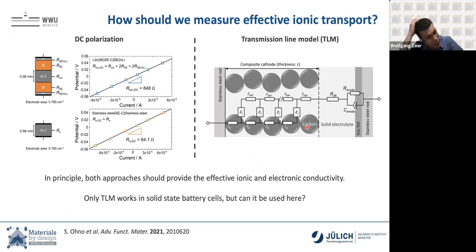Now there's in principle 2 ways that we can measure this. The simpler way that we use most of the time is so-called DC polarization. In the end, you polarize your setups with an electron blocking current collector and an ionic blocking configuration, and you just measure ion currents. So you use Ohm's law and you get a resistance out, and with that resistance we can calculate an ionic and electronic partial conductivity. This works in pure composites. It does not work in full cells. In full cells, what one can do is use the so-called transmission line model, where we model this complicated multi-phase behavior in the cathode composite as a bunch of ion conducting resistances, a bunch of electronic conducting resistances, and transverse impedances in between.